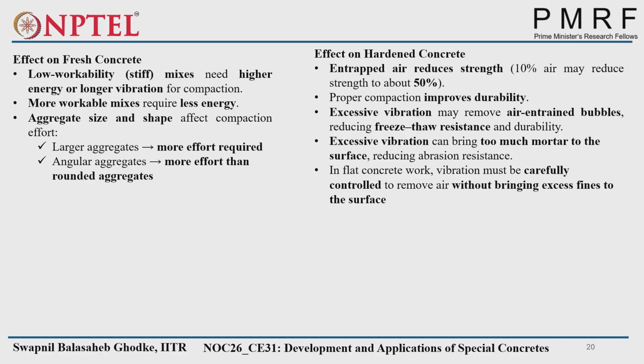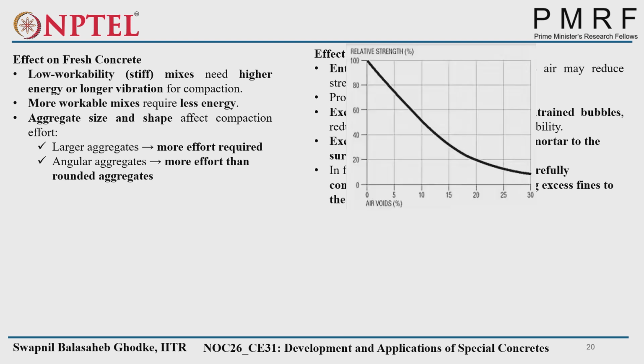So if we do not properly do the compaction of the fresh concrete, what happens in the hardened concrete? That entrapped air reduces strength almost 50% for 10% of air. Proper compaction improves durability due to the reduction of the voids. Excessive vibration may remove air entrained bubbles, reducing freeze thaw resistance and durability also. Excessive vibration can bring too much mortar to the surface and create laitance on the surface, reducing abrasion resistance. So, vibration must be carefully controlled to remove air without bringing excess fines to the surface.